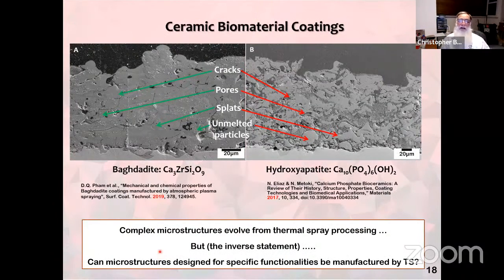So here's some more recent work, the last few years. Now, this is a bioceramic coating, both produced at Swinburne. There's the traditional gold standard of hydroxyapatite, calcium phosphate, which has been sprayed on roughened titanium, Ti64, titanium 6 aluminium 4 vanadium. And now here's the new material, Baghdadite, calcium zirconium silicate. And you can see these architectural features, which all of these now have an attribute. They are highly desirable features within this very special coating that you could be wearing one day, or maybe your parents or grandparents are wearing one already. So the Baghdadite: cracks, pores, splats, and unmelted particles.